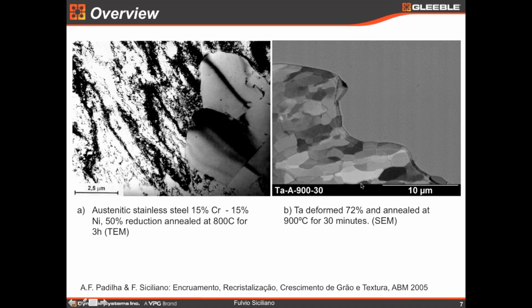The same thing here. This is tantalum metal deformed at 72% and annealed at 900C for 30 minutes. We can also see the recrystallized grain with a very small quantity of defects. We can barely see anything here, and it's growing over the subgrains. In this case, we have subgrains formed, and this is because of the high stacking fault energy of tantalum as opposed to stainless steel. So this is basically what we can see when you look at the microscope. This is a transmission electron microscope on the left and a scanning electron microscope on the right.